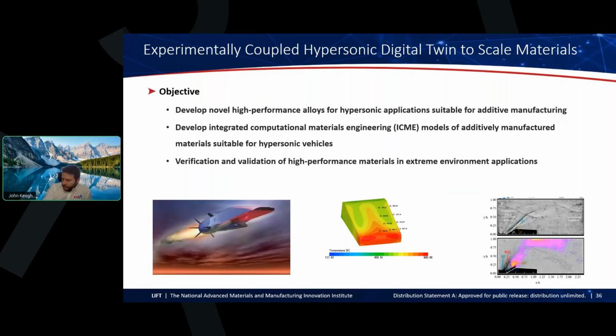One thing I want to say: there are actually multiple material systems that we investigated here. One of the success stories that came out of this, we wanted to modify a COTS alloy to make it more printable for additive manufacturing and also mitigate the need for post-build heat treatment. And we did that successfully. We made that alloy and made parts, tested the parts, all your quasi-static testing, but we also tested them in a real environment. So there actually is a real success.